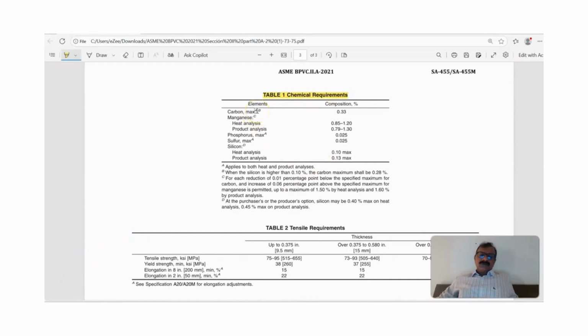As you can see, there are notes A, B, C, D. Carbon, phosphorus and sulfur have got note A. That means it applies to both heat analysis and product analysis. Then you can see the silicon content for heat analysis is 0.1 and product analysis it is 0.13% maximum. But you can see note D: at the purchaser's or producer's option, silicon may be 0.4% max on heat analysis and 0.45% maximum on product analysis. So this 0.10 and 0.13 can be changed to 0.4 and 0.45.